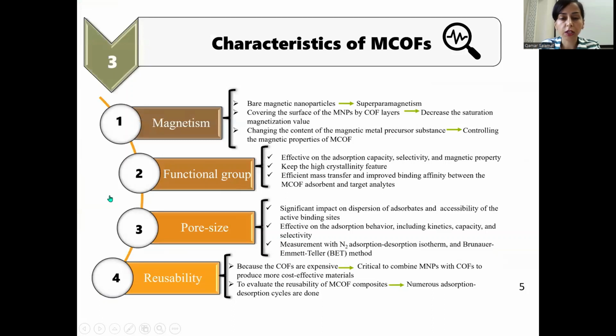Magnetic covalent organic frameworks have very outstanding characteristics like magnetism, functional groups, pore size, and reusability. Regarding the magnetic features, this feature is typically evaluated at room temperature using a vibrating sample magnetometer, abbreviated as VSM. If there is no apparent hysteresis in the curve, it means that this material has superparamagnetism like a bare magnetic nanoparticle. But by covering the surface of the magnetic nanoparticle with COF layers, we can see a decrease in the saturation magnetization value.